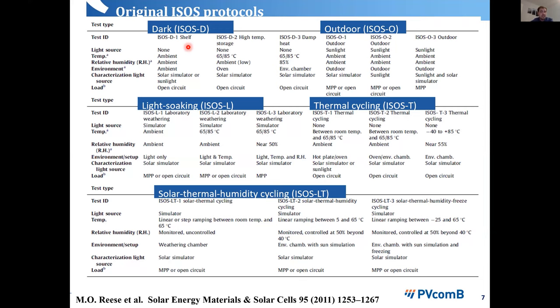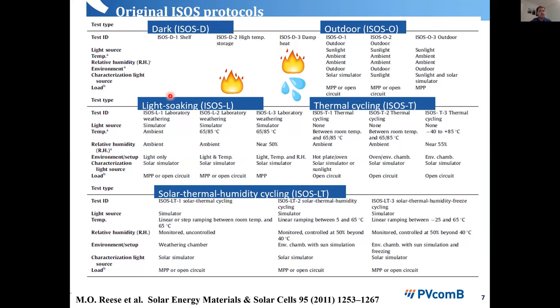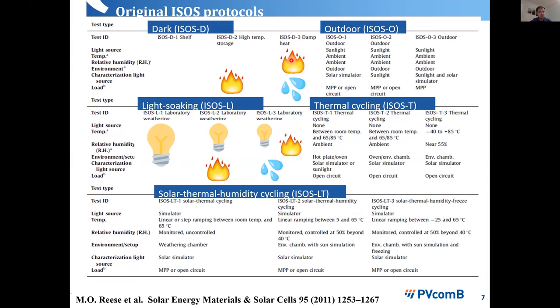Each of these families has three different levels of sophistication indicating how much equipment you need and how harsh the test is. For dark storage, level D1 uses ambient atmosphere and ambient temperature monitored but not specifically controlled. Level D2 introduces a hot plate or some means of heating the sample. Level D3 controls both high temperature and high humidity, ending up with a damp heat or 85/85 test. Similar logic applies to other testing families like light soaking.